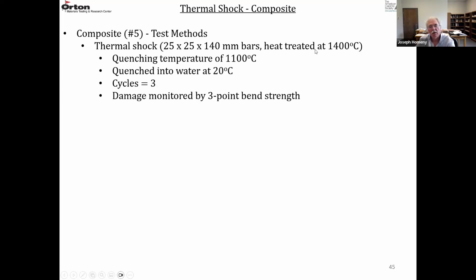So the bars that were heat treated at 1400 degrees C, the 25 by 25 by 140 millimeter bars, were thermal shocked. They were quenched from 1100 degrees C to 20 degrees C in water, subjected to 3 quenching cycles, and then 3-point bending was used to monitor the damage to the 3-point bend strength.